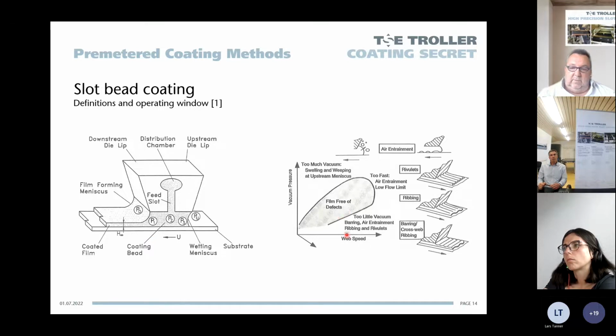Here is a coating window, so we have web speed down here and vacuum pressure, which would be the upstream air pressure. But we could also replace that by flow rate. Then the picture looks exactly the same. And you see, as long as you're within this coating window, your coating is free of defects. You have a stable and uniform coating. When you're going out, depending on which location you're going out, you have maybe air entrainment, or defects like this, lines in machine direction, or sometimes also crossweb direction.